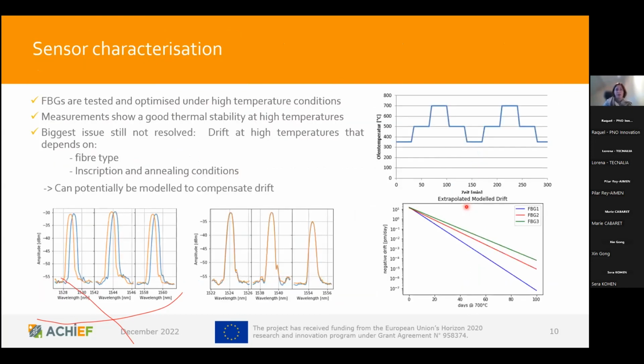So, some further sensor characterization experiments here. Here we expose the FBGs to a defined set of temperatures up to 700 degrees Celsius and look at the wavelength shift that occurs in the reflection spectrum. On the bottom left corner, you see that there is a shift in the Bragg wavelength before and after annealing at 700 degrees, to a larger or a smaller extent, depending on the FBG. And this drift is well known in temperature. It results from relaxation processes within the optical fiber and cannot be gotten rid of at these high temperatures.